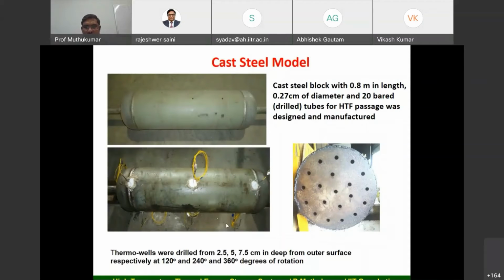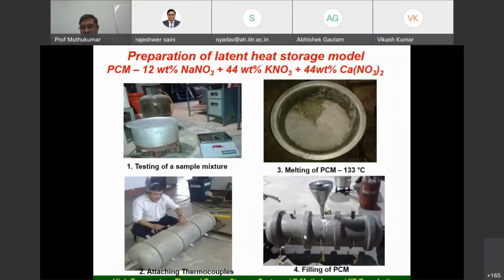To measure the temperature history, we have different thermocouples inserted at different radial as well as axial distances. So they can be used for validating our thermal model. And here you can see the PCM. There are 3 compartments. In each compartment, a different PCM can be filled. So when you are filling it, you have to melt the PCM, and then in the form of liquid you have to pour it inside. So we have to be very, very careful. Here we are taking 12% NaNO3 and 44% CaNO3, and then the remaining about 38% will be the potassium nitrate.